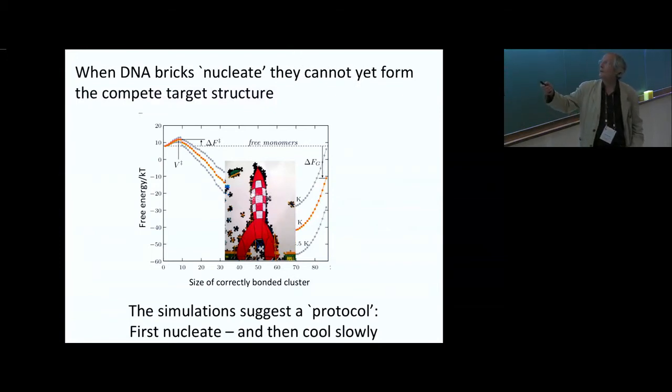If you're here, then basically, well, it was a puzzle, it would be easy, but with assembly, there's one and only one position where you can attach another particle. So entropically, it's very difficult to complete your puzzle. And that's why the free energy goes up as you approach completion. And that's why you actually have to cool down to get the complete structure.